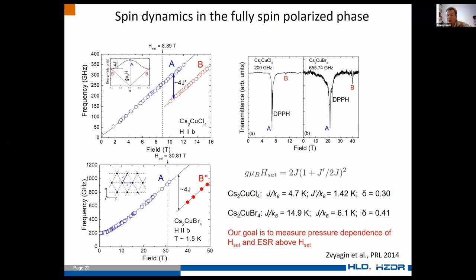When looking at the difference between these modes, we can estimate J prime, and this is very good. This was applied to cesium copper bromide and cesium copper chloride. You can see here two different materials, and this splitting in the fully spin polarized state gives you J prime. Then, if you know J prime, you can look at the saturation field and get the exchange parameters J and J prime.